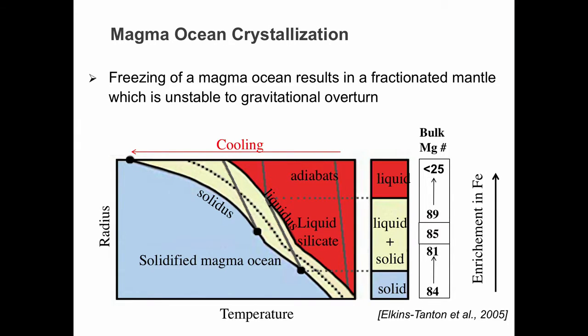But you see at the surface you have a more iron-rich and more dense material, which you can imagine is unstable. Having heavy stuff close to the surface and lighter stuff at the bottom, that material will sink, if it is possible to sink, if you have a low viscosity and you can bring that stuff down. But that's typically what we assume can happen. So in other words, this heavy stuff sinks down and ends basically at the base of the magma ocean or wherever it started to crystallize.